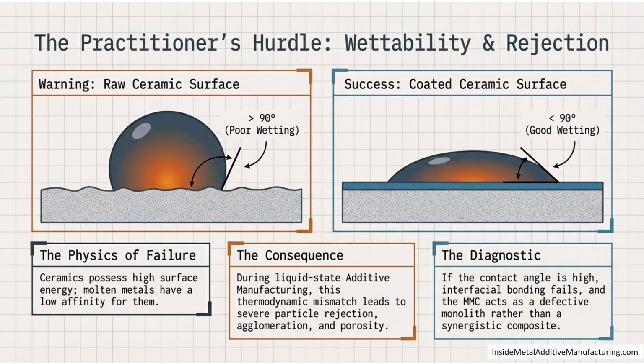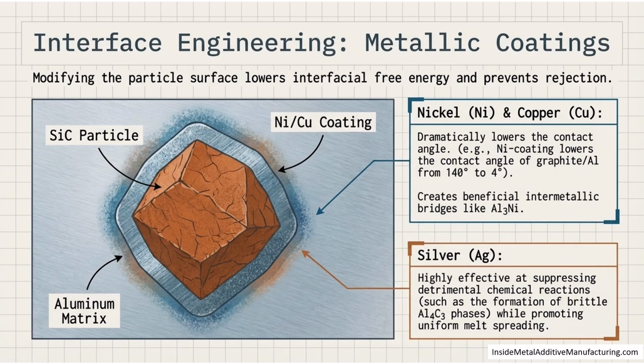As practitioners, our greatest hurdle is the thermodynamic mismatch between molten metals and ceramics. Raw ceramics have high surface energy and low affinity for liquid metals, leading to poor wetting, angles greater than 90 degrees. This leads to particle rejection and porosity. To move from a defective monolith to a synergistic composite, we must lower that contact angle. The solution is interface engineering.